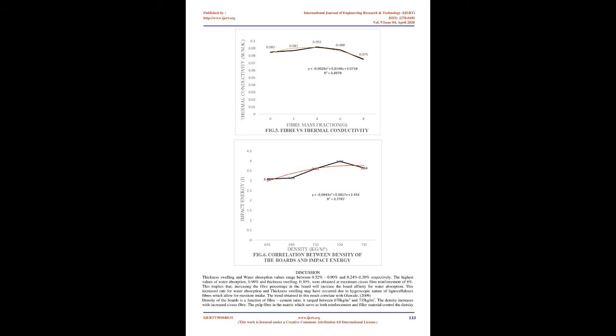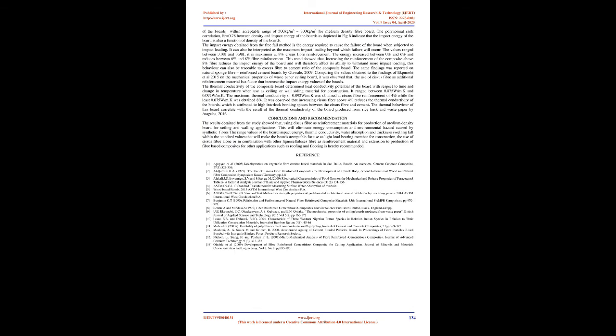This trend showed that increasing the reinforcement of the composite above 8% fiber reduces the impact energy of the board and will therefore affect its ability to withstand more impact loading. This behavior can also be traceable to excess fiber to cement ratio of the composite board. The same findings were reported on natural sponge fiber reinforced cement boards by Olaoye, 2009. Comparing the values obtained to the findings of Akinbosoye et al., 2015 on the mechanical properties of waste paper ceiling board, it was observed that the use of Cissus fiber as additional reinforcement material is a factor that increases the impact energy values of the boards.